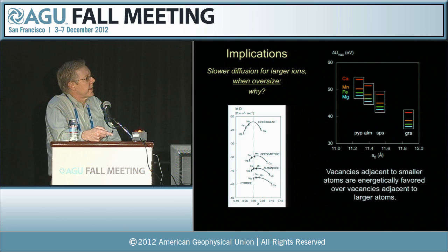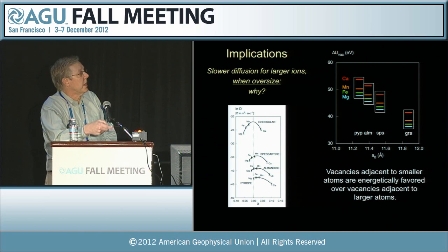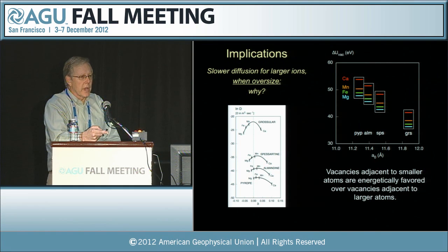And the explanation for that, I think, cannot be migration energies, which was what elastic strain theory would predict. Instead, it has to be related to what we see here, that the vacancies adjacent to smaller atoms are energetically more favorable, lower down, than the vacancies adjacent to larger atoms. So once again, it's the local vacancy concentrations that impact the diffusivities.